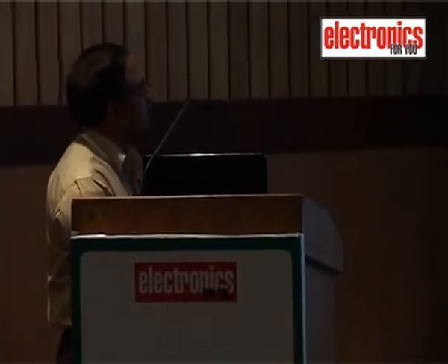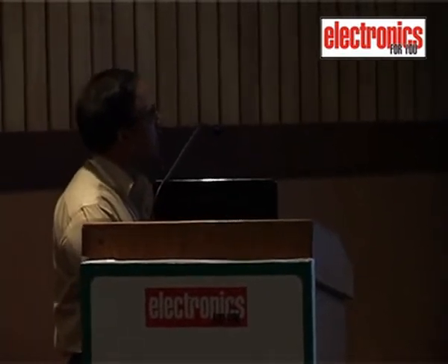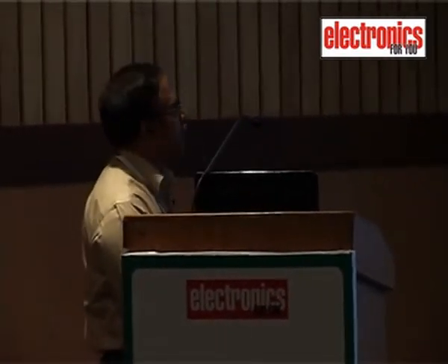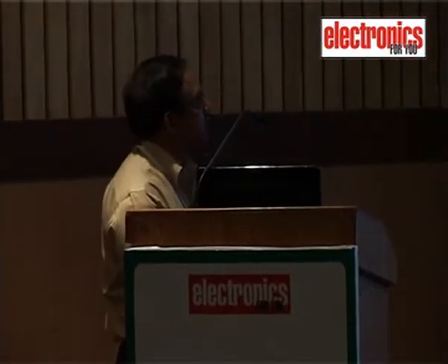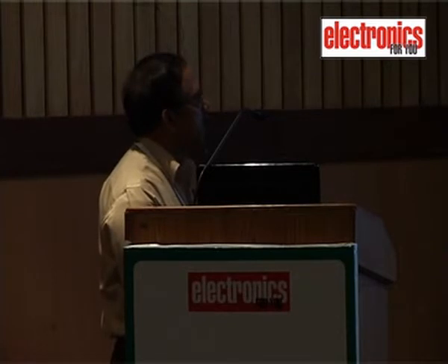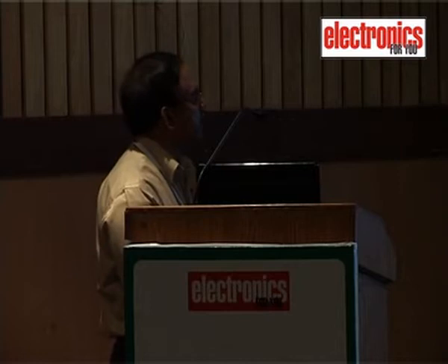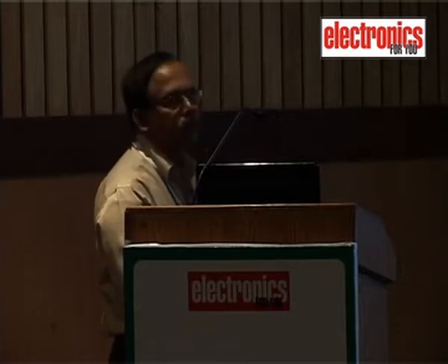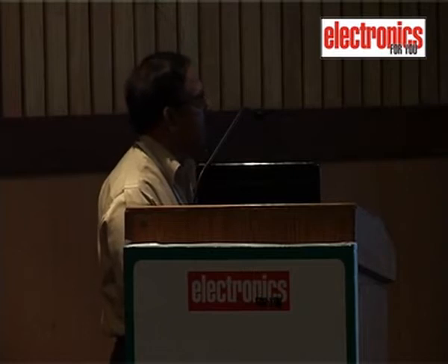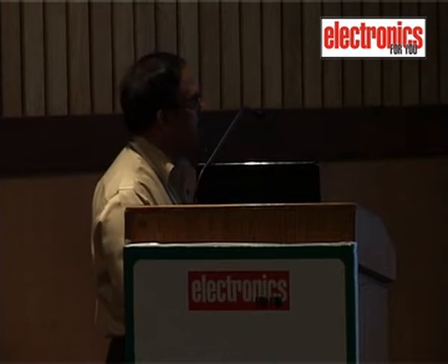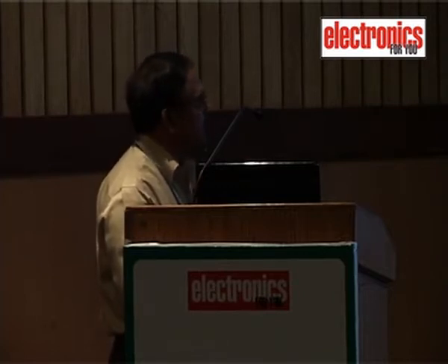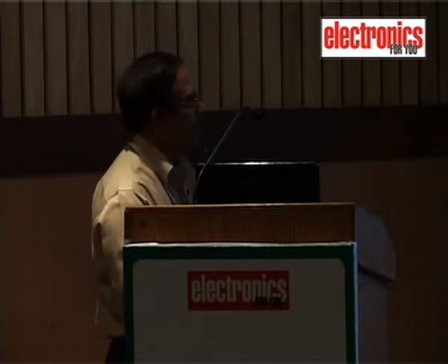And we do group B testing, where, as I have already explained, peel strength is important for SMD type of components, and bond strength is important for plated through holes. Solder float tests are important for rework simulation and soldering, and interconnection resistance is one which varies during various environmental tests, and insulation resistance to see the withstanding voltage, and dielectric withstanding voltage to see whether the insulation provided is adequate or not, and finally we do microsectioning, which is a vital thing which reveals most of the defects.